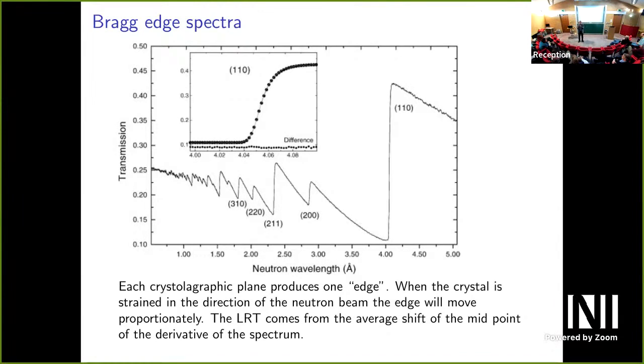And because we've got crystals in all directions, there'll be quite a lot in any direction, including ones which are lined up to that Bragg angle. So what happens is you get jumps in the spectrum that correspond to the distance between the crystallographic planes. Okay? In that image.